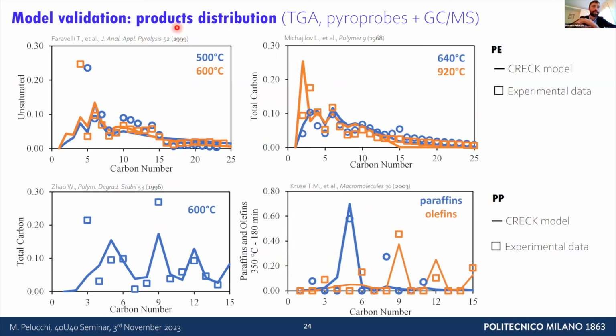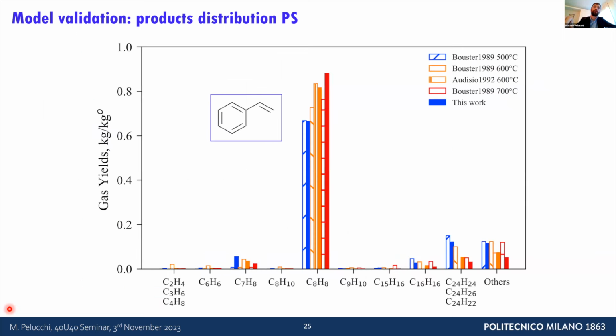Then, of course, we can discuss whether the model is good or bad. There's some deviations if you think about, for example, the C2 and C3 fragments in polyethylene and polypropylene. But at least we get this dependence and in good agreement with the experiments of the product distribution from the operating condition of the pyrolysis process.